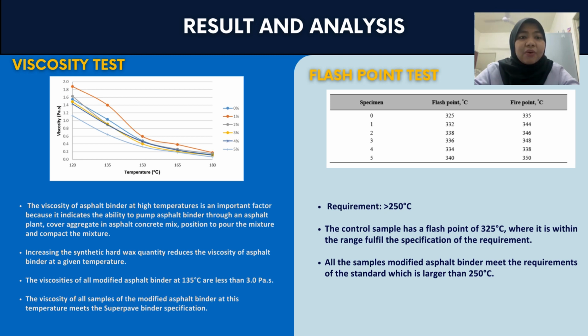The viscosity of all modified asphalt binders at 135 degrees Celsius is less than 3.0 Pascal second. 135 degrees Celsius is used because it is the minimum temperature of the viscosity test in the performance graded asphalt binder specification. The viscosity of all samples of modified asphalt binder at this temperature meets the Superpave binder specification, which is 3.0 Pascal second. Let's move to flash point.